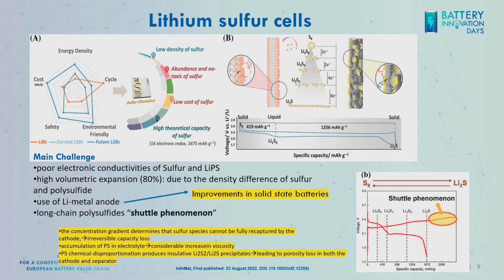On one side, and I will not say anything about it, we have metallic lithium, and so all the issues already discussed yesterday during the solid state talk about metallic lithium are also present here. So dendrite formation, high reactivity, and so on are always there. So we need to protect metallic lithium in order to make it work and to be very safe. So all the improvements I highlighted in yellow, all the improvements that are coming from the solid state sector, will be useful and easily translated here. So that's good.